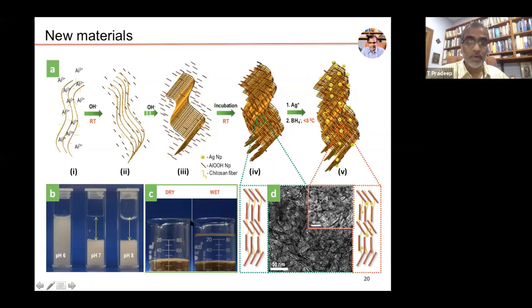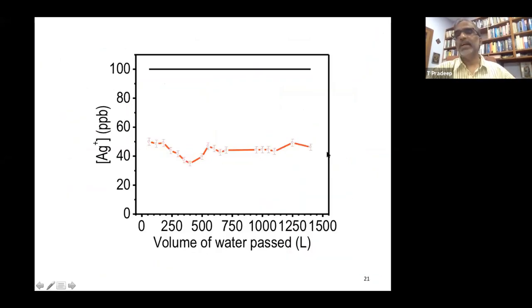And why is that possible? In this particular case, it is possible because of biotemplating, and we use biopolymers for that. You create aluminium oxyhydroxide nano sheets of about 50 nanometers long and 15 nanometers wide, and you create matchboxes. If you assemble 6 sheets, you can imagine how a matchbox can be constructed. And within these matchboxes, you can embed nanoparticles. A number of nanoparticles can certainly be made. Let us say we put silver nanoparticles.